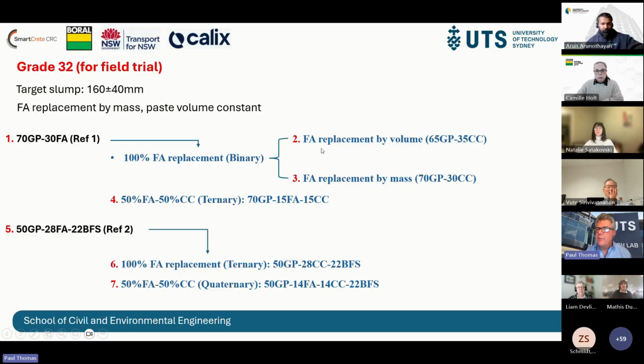We initially replaced it by volume. Of course, calcined clay is more dense than fly ash, so we needed to incorporate a higher mass to replicate the volume substitution. We found that this was over-substituting, and the workability deteriorated a little too much. On a mass basis, it worked very well.